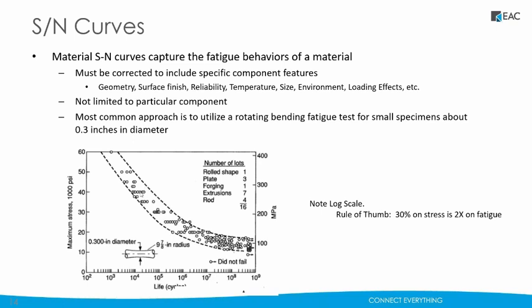The common mistake I see in industry is people using that SN curve without taking into account that the specimens used to generate such a curve were, generally speaking, smooth, polished specimens at room temperature. Whereas what we have is usually an unpolished specimen, and there's also going to be variability in the field. If you have 1,000 products, sometimes 1 in 100 failures isn't acceptable.